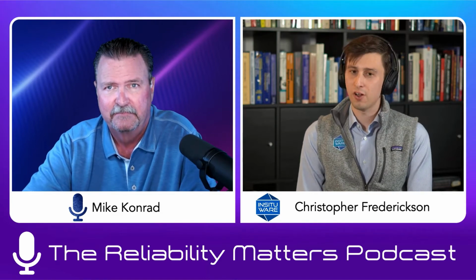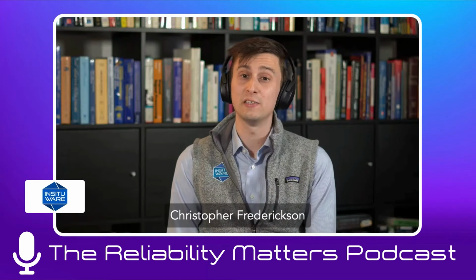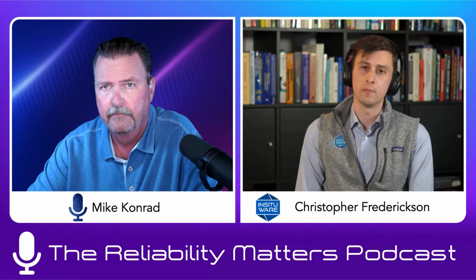Yeah, what we have done when it comes to customized solder paste is we've had that sample of that material sent in, and we've run through that torture test on that paste as well. You can go through and run the measurement on a custom paste without doing that torture test. You just lack some of the additional context surrounding that measurement. So you'll get back a number on what's in essence, how active is this solder paste, but you lack the context of, is this a good value or is it bad?